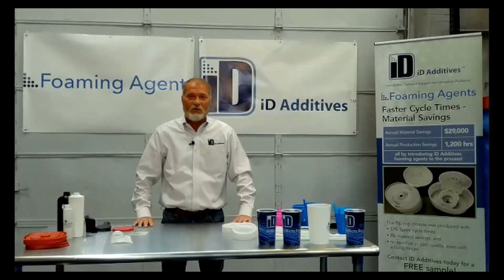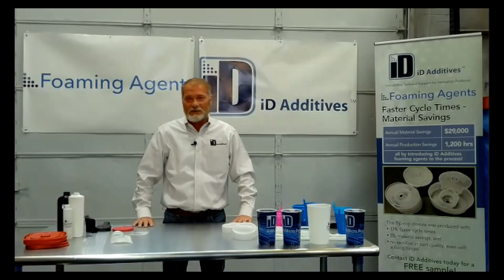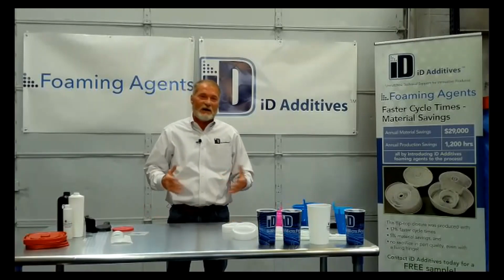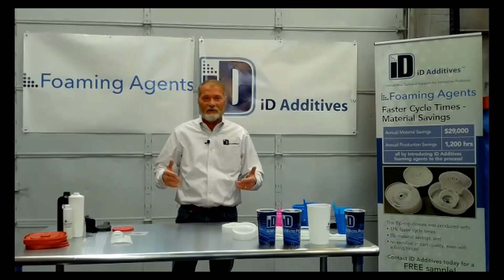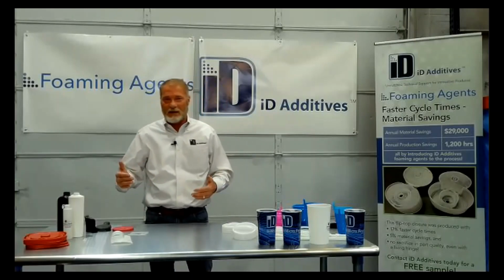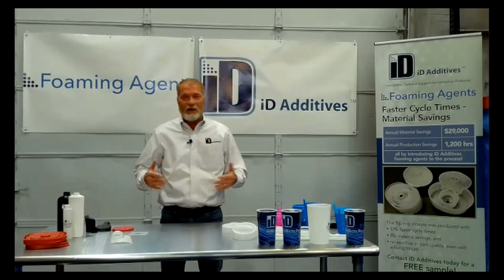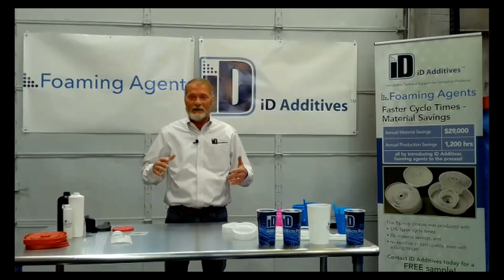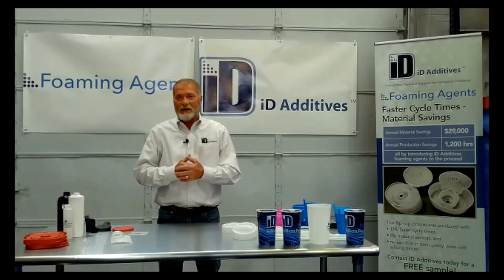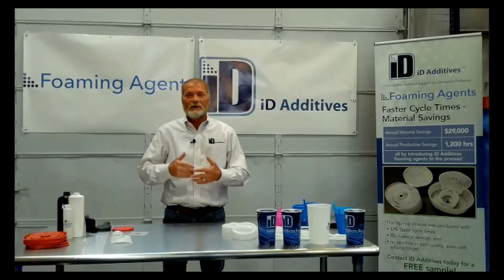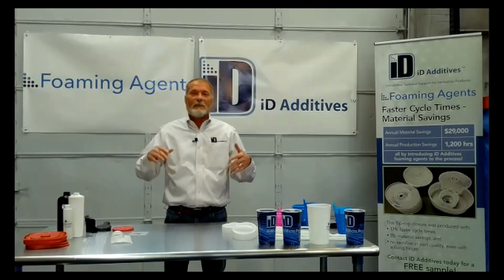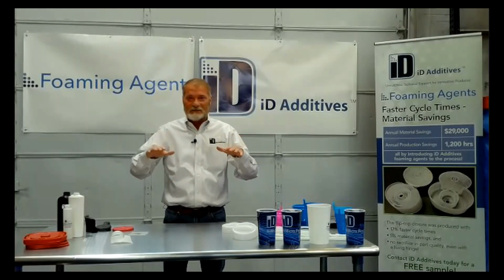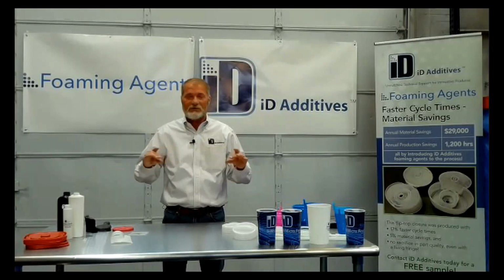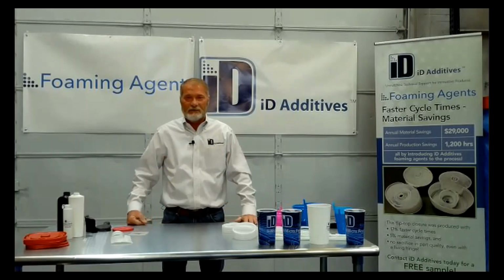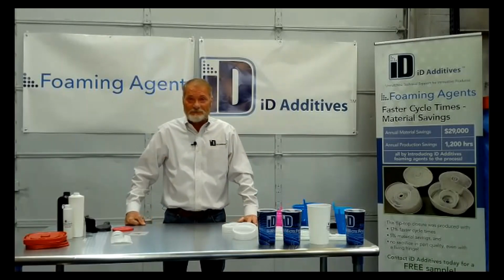Again, you control pressure, you control the temperatures, and if it's a mono layer, I don't know if you're doing a mono or an ABA, but either way, with a mono layer, keep that pressure on the screw and control temperatures, and you'll get a really nice, clean, very tight cell structured styrene part. And it does foam extremely well.